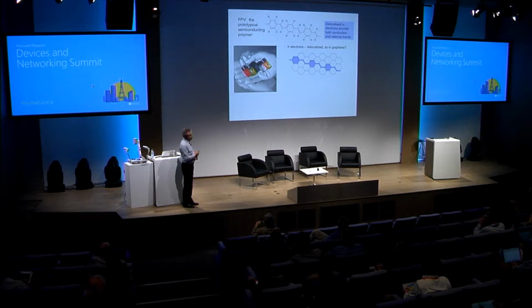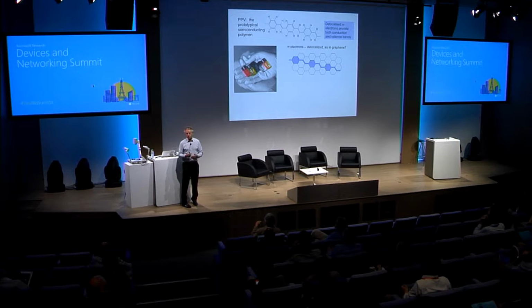So these are some little images of different semiconducting polymers. They're more or less all the colors of the rainbow. But what you see is that unlike silicon, which comes in a block, a crystalline block, which is sliced into a wafer, and then wonderful things are done to a wafer of silicon, but it's all a high temperature, usually high vacuum process. Here we have semiconductor dissolved in a common solvent. We've now got semiconductor as paint. So semiconductor as paint, if it turns out to be useful semiconductor, and that was a big if, is fantastic, because we can now use a completely different toolkit to start assembling this stuff into useful devices.